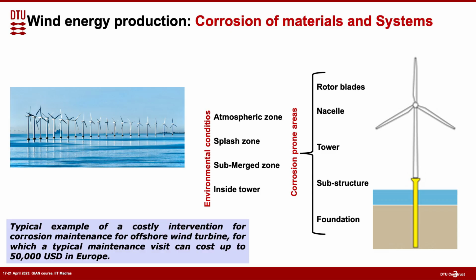Alternate wetting is one thing, and also because of the higher amount of oxygen that is coming, you have a higher corrosion problem. That is the splash zone corrosion issue. And then we have the atmospheric zone, which is mainly the nacelle part, where the aerosols and things like that come up, and that way you have the corrosion problem in the nacelle. So that's the way we can divide the corrosion problem in the wind turbine.